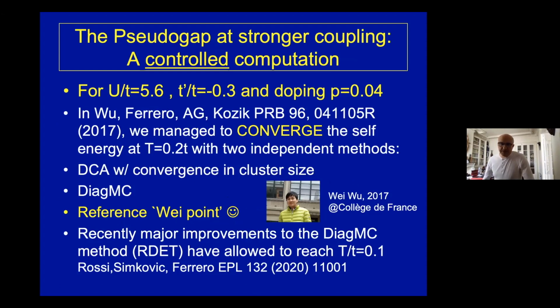And to be a little more realistic in the context of cuprates, the results I'm going to show you are for a pretty large T prime over T, appropriate for hole-doped cuprates, and a very low doping, 4%. And I would like to show you that in this regime, one can actually, in a controlled computational way, nail down the existence of strong coupling pseudogap by two different methods with quantitative agreement, one being the cluster extensions in the DCA flavor of dynamical mean field theory converged in the cluster size, which is a pretty formidable task, not possible for very many parameter ranges, but possible for that one, and diagrammatic Monte Carlo methods.